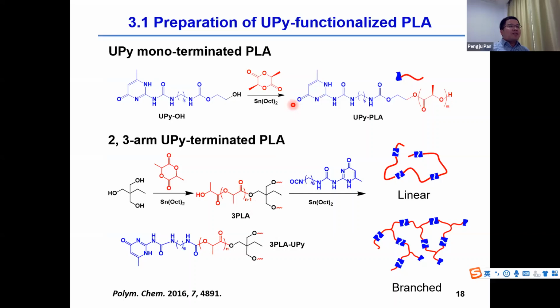In order to introduce the UPy unit to the chain end of PLA, we synthesize a hydroxyl functionalized UPy and use it to initiate the ring-opening polymerization of lactide. This gives the polymer mono-terminated by UPy. On the other hand, we synthesize the two-armed PLA and three-armed PLA terminated by hydroxyl group and then convert the end group to UPy. This gives the polymer with 2 or 3 UPy terminals.